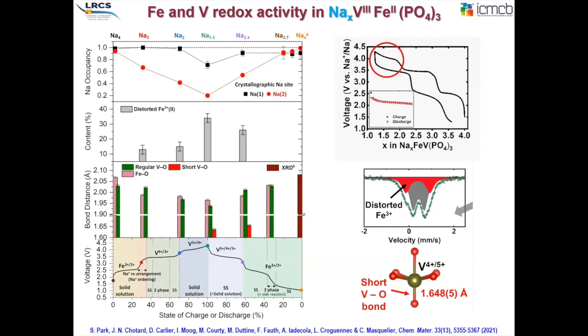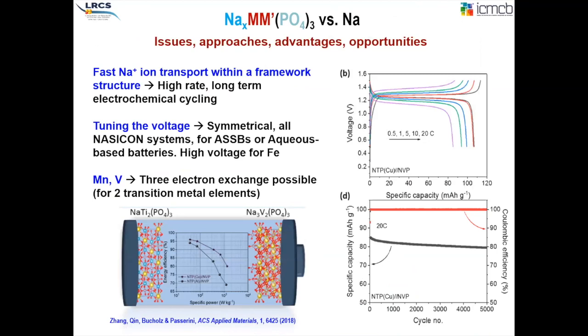At the end of charge, very interestingly, we were able to identify again very short vanadium-oxygen vanadyl-type bonds that occur at the end of charge and that are mostly responsible for the structural irreversibility upon the next discharge. So I will conclude about the NASICON phases, just to remind everyone that indeed this structural family that has been identified for very fast ion transport as a solid electrolyte is also a very good fast-rate material for cathodes in sodium-ion batteries.